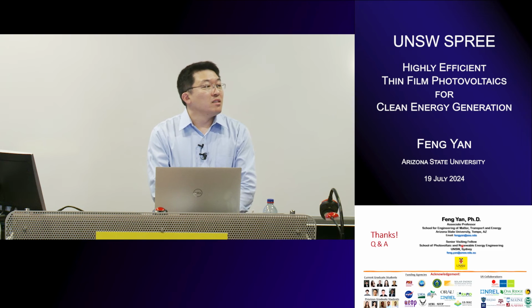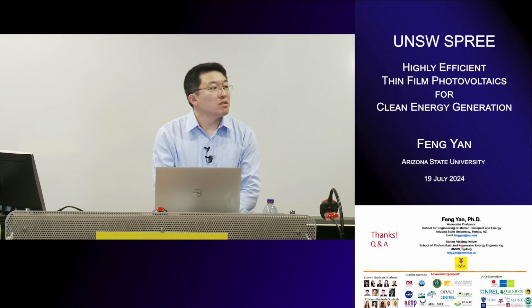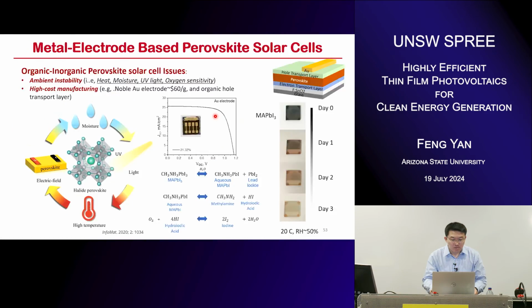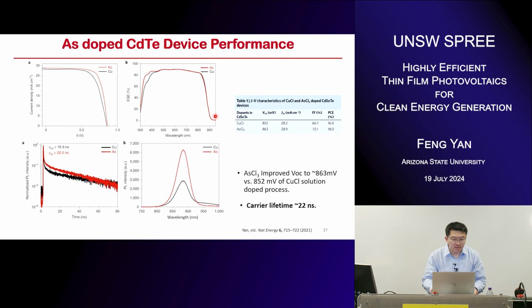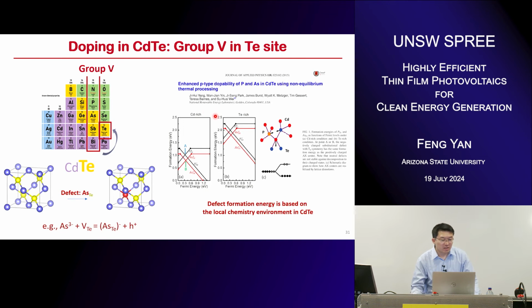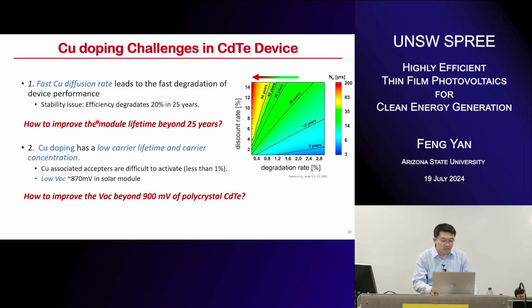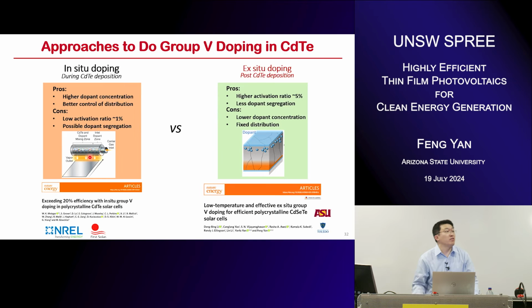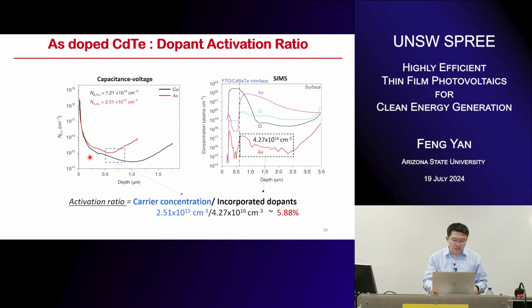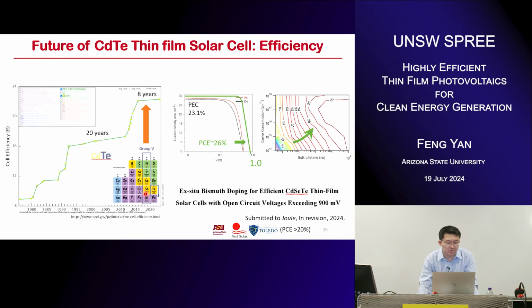Yeah. About the group 5 element doping. I see you tried different elements in the work. Yes. So initially we tried arsenic, because arsenic was demonstrated in the in situ doping work using cadmium arsenide to dope, and we focused on arsenic initially. But during our work, we also tried different ones, for example phosphorus, antimony, and bismuth. We demonstrated this work, which is in revision, using a different bismuth salt.